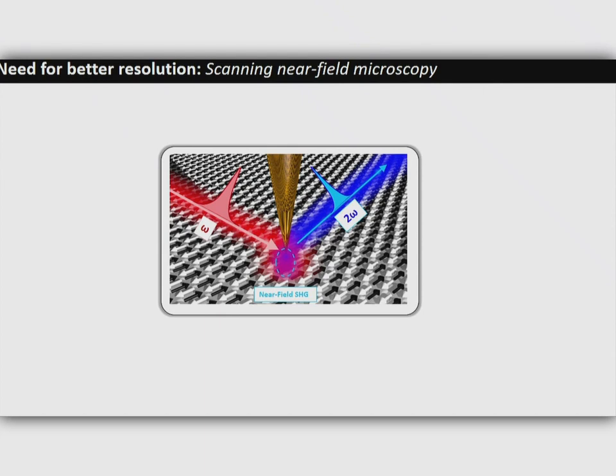And recently, we want to move from far-field imaging to near-field imaging. So we have acquired an apertureless SNOM, and the principle is the following. You shine light on a metallic tip, and the electric field is enhanced at the apex of the tip. What's happening here is like if you had a nano lamp that you scan around the sample. And this tip also acts as something which scatters the near-field light, which you can then collect. So this is the idea.